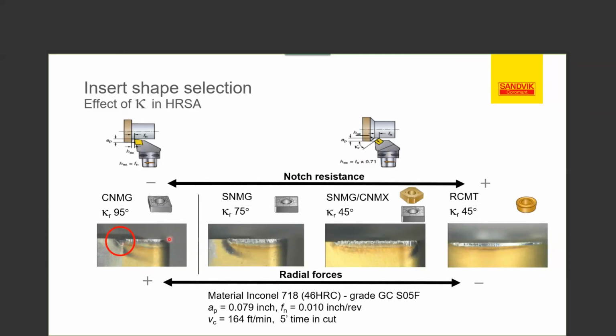And as you see, as we steer the insert to more of an entry angle, on an SNMG at 75 degrees, we still got quite a bit of flank wear. That's because of the heat buildup in the cutting zone. But as we change that entry angle to a 45, you can see that's a lot less. And we've actually elongated that area we were talking about earlier, so we're dissipating that heat over a longer area. On a button insert, same thing, very similar to the SNMG style insert. We're making that area a lot longer, again dissipating the heat.